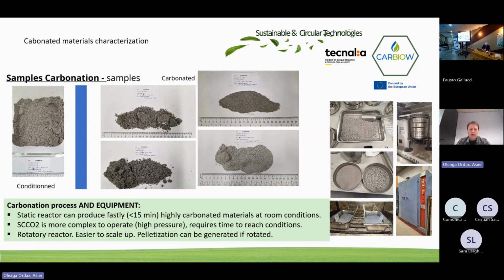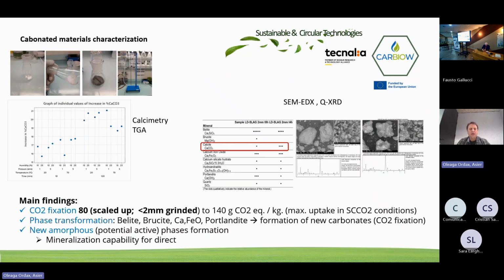The results are that the static reactor went very okay. We captured close to the maximum. With the supercritical, we were really close to the maximum expected capture, but it's more complex with difficulties getting to the right conditions without any issues. The reactor must be really well tuned and demands a lot of energy. And the rotatory reactor worked very well, very scalable, with similar results as the static reactor of smaller scale. So we have as a result a granular material that was carbonated.